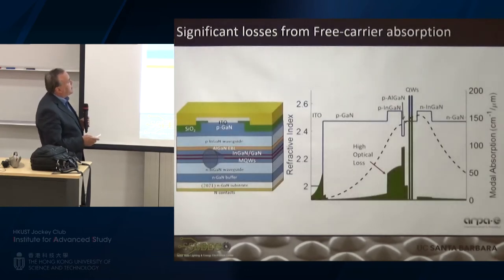So how do we improve on that? For the epi guys, one of the things we modeled is where the high optical loss was occurring. This shows the modal, the actual blue laser mode. The optical loss was coming from the p indium gallium nitride waveguide here and the p-GaN. So we re-optimized it, lowered the doping here, and even lowered the silicon doping because there's a lot of loss there. That's a trick we learned from the telecommunications industry: the free carrier loss, that is absorption of the free carriers on the N and P side, limits your lasers. If we can continue to do that, these lasers will eventually be 80% efficient, which is what they are in gallium arsenide. If we get to 80% efficiency, these lasers will be as efficient as LEDs.